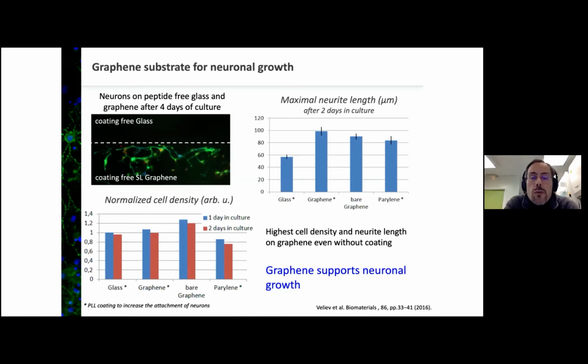And the reason for that was not very clear, but one possibility is that graphene is a conductor, so it promotes interaction between cells, but also something very important is that the binding strength of graphene, so the nanomechanical property of graphene, exactly match the binding of a phospholipidic bilayer, which forms the cell's side walls. So this matching of properties is actually very important and probably one of the reasons of the biostimulation of the high biocompatibility of graphene.